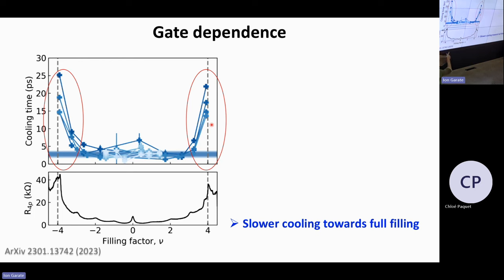So and actually the answer is a little bit here as well. So things do depend on, you know, the Moiré pattern, because there's something going on when you fill this unit cell of the Moiré pattern with 4 electrons. So there must be something related with this Moiré pattern. So you very clearly see this. So it's not something that the twisted bilayer graphene is more defective or more disordered. It's really something that's tunable just by gating, and you can actually get very long cooling. So it's not an effect of just having bad quality material.